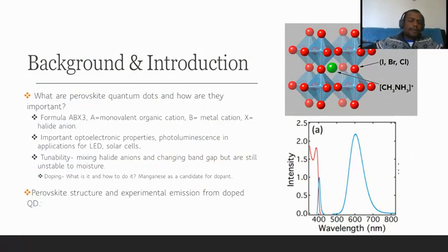Next slide, okay. So what are perovskite quantum dots? Perovskite quantum dots are quantum dots or nanocrystals having the structure shown at the top right image. And this structure was named after the mineralogist who found it, Lev Perovsky. So it has a formula of ABX3, where A is the monovalent cation, shown in green in the image, which also can be replaced by an organic cation, and B is the metal cation, which is the center of the octahedral sites in the image, and we have the halide anions, which are the red ones at the edges of the octahedral sites, and so they are very important nanocrystals.